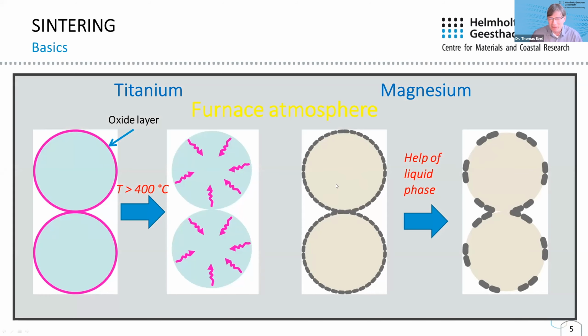In principle, it is even a little bit more complicated, because this whole sintering process takes place in a furnace, and the furnace does not have a really clean atmosphere. You have oxygen and you have carbon from the binder, and so on. The trick is really to avoid that these elements again pollute the surface, and that's a little bit tricky and needs a little bit of experience.